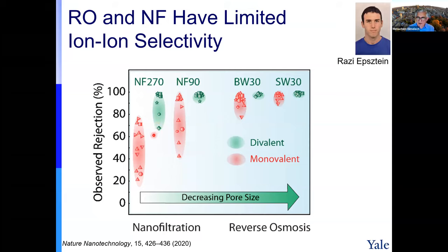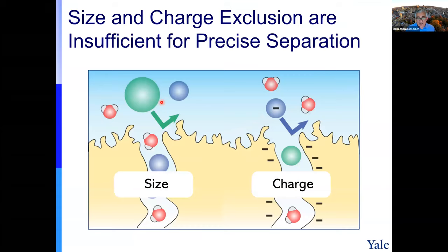But here we are looking at something even more complicated. What would be the selectivity between monovalent ions? If I have lithium and sodium, I want to separate between them. And the reason is that the mechanisms are not straightforward. I mean, this membrane works on either size exclusion or charge, and this is not enough to get the right selectivity. You need something more sophisticated.